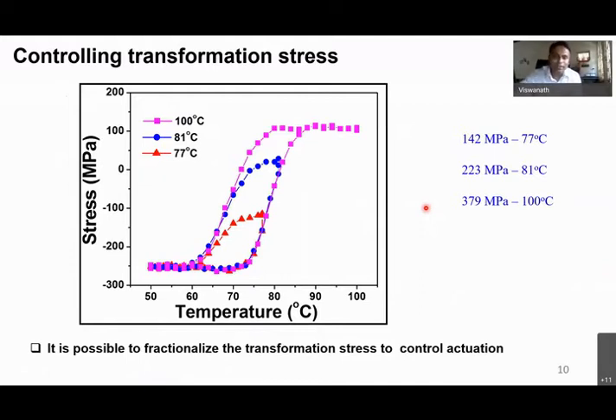So we have, for example, grippers or some actuators where we want to control a specific stress or specific strain. In that case, we can actually arrest the temperature. Instead of going all the way from 50 to say 100 degrees Celsius, I can stop somewhere in between and come back. So it is also possible to fractionalize the total transformation stress by choosing the right temperature across the transition boundary.